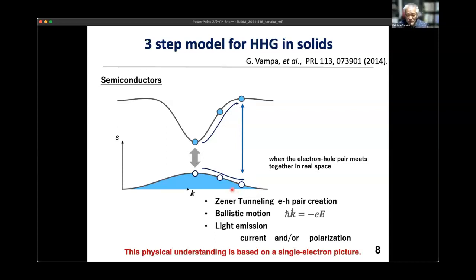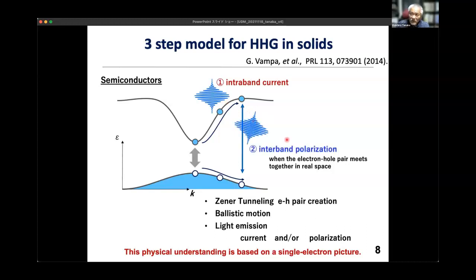People note that under the acceleration process, we can expect some nonlinear current, and this also gives high harmonics. And the recombination process also gives high harmonics. So in conventional semiconductors, people consider that we may separate the high harmonic spectrum into 2 parts: an intraband current part and an interband polarization part. But typically these 2 parts interfere, and for the spectrum we must consider both.